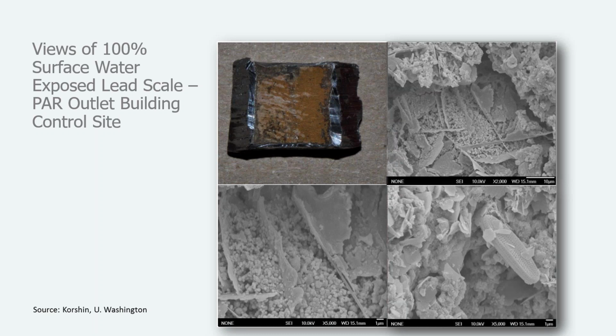And here's just one more picture from the control building, a picture of the pipe loop there, pipe coupon. You can see it looked very similar to the phase 1 from the Hood Street building, where we had a lot of lead 4 in presence of, in this case, hydrocerussite, and you can see very clearly the crystalline hydrocerussite and all this lead 4 forming around and depositing around the scale. And I included this picture because after 100 plus years of being unfiltered, there's some diatoms trapped in the scale, so it's sort of interesting to see.